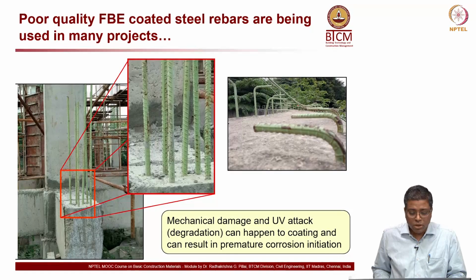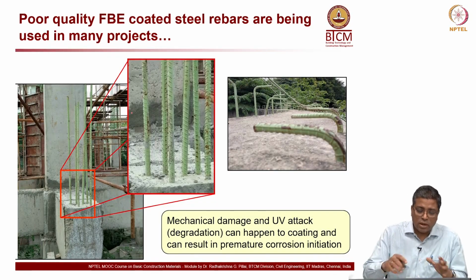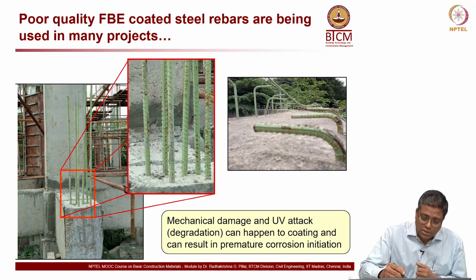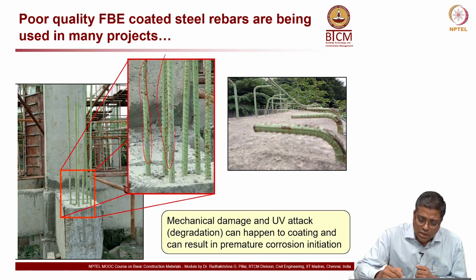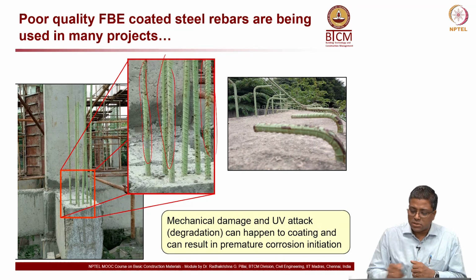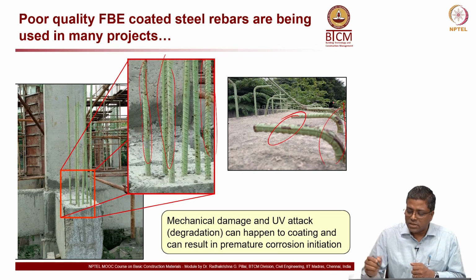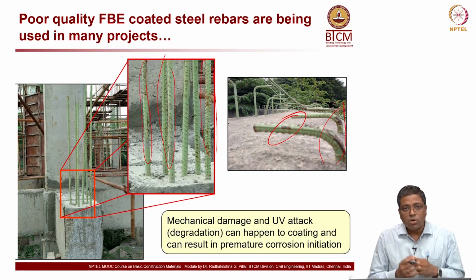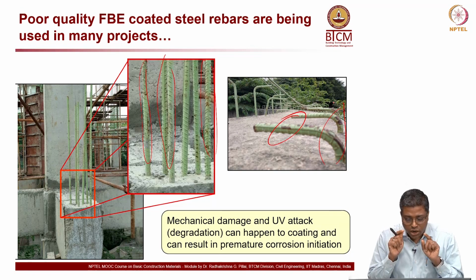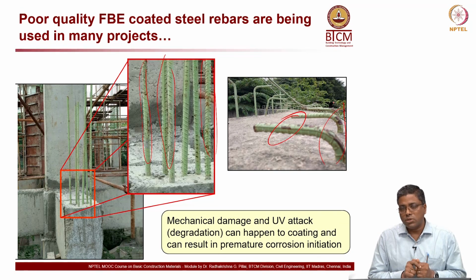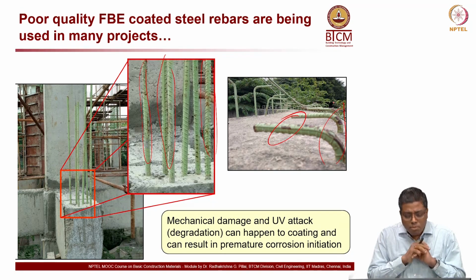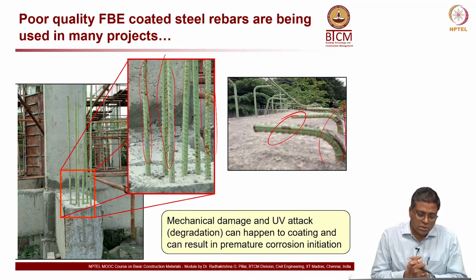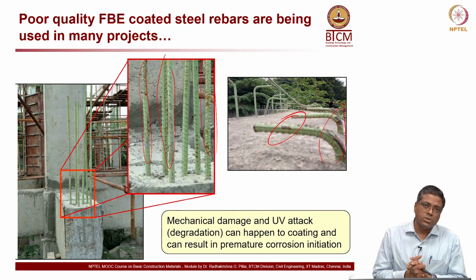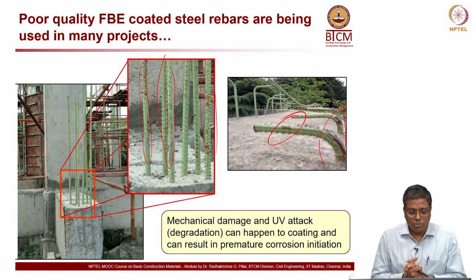So I am going to show you some more cases where these bars are exposed, and you can see that there are a lot of brown lines, brown things which you see on these bars. You see here, it's all very severely damaged, but they are unfortunately being used in our construction. So as a technology, epoxy coating is very good, but it is not being used in a proper manner on our construction sites, in most of the sites. I am yet to see a construction site which is using good quality epoxy coating or epoxy coated rebars.